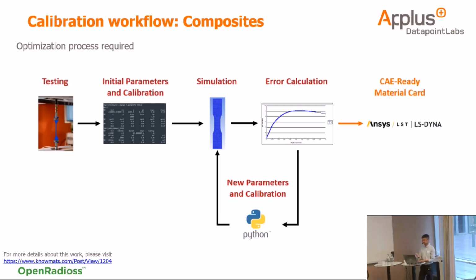Usually, MAT 58 or MAT 25 is pretty straightforward from the data. But then sometimes, if you want to include some damage evolution, crack propagation, or delamination, you also need to do some iterations on your process in order to get the right parameters and adjust whatever you need to. For all these iterations, we have developed our own tool, mostly in Python. It's been integrated for LS-DYNA and OpenRadioss, so we can run all our simulations through this iterative process and be efficient in this way.